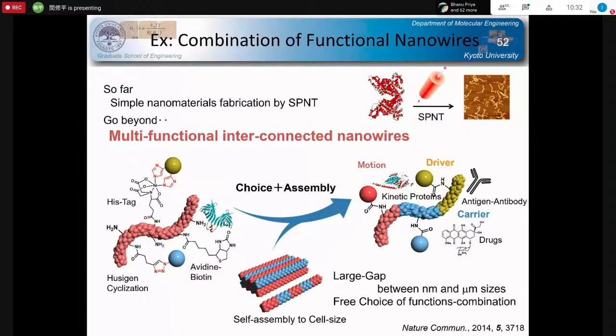And the next question is, can we prepare the graphene oxide carbon nanotube by the SPNT method? Well, this is a very good question. Here, for the polymerization reaction mediated nanomaterial fabrication, at first we focused on the Buckminsterfullerene systems. This is the reason why we would like to realize carbon-based nanomaterials, because Buckminsterfullerene is principally a carbon allotrope. After the successive formation of the carbon-based one-dimensional nanostructures, in principle it is possible to fabricate a graphene oxide system, because the oxidation reaction of carbon-based nanowires is very easy using a variety of chemical treatments. So in principle, I should say yes, we can prepare graphene oxide in the future.